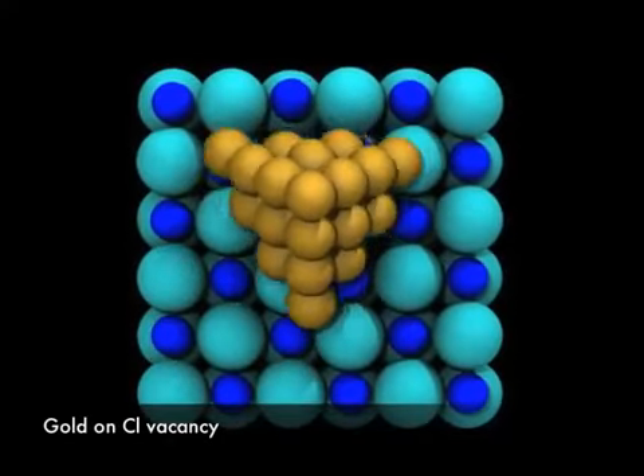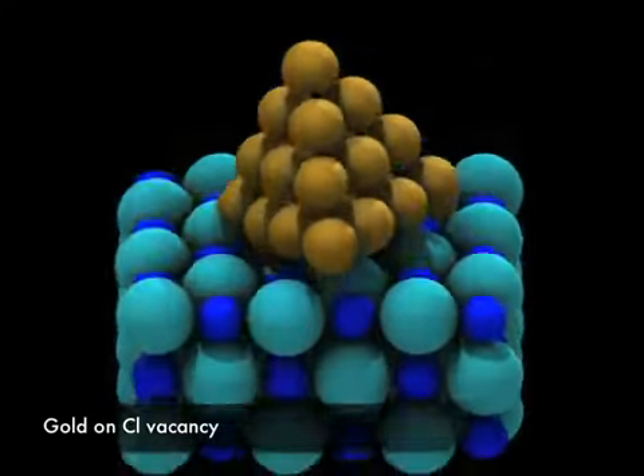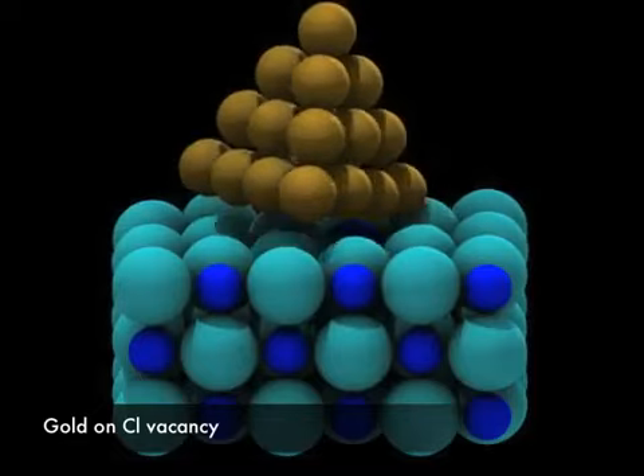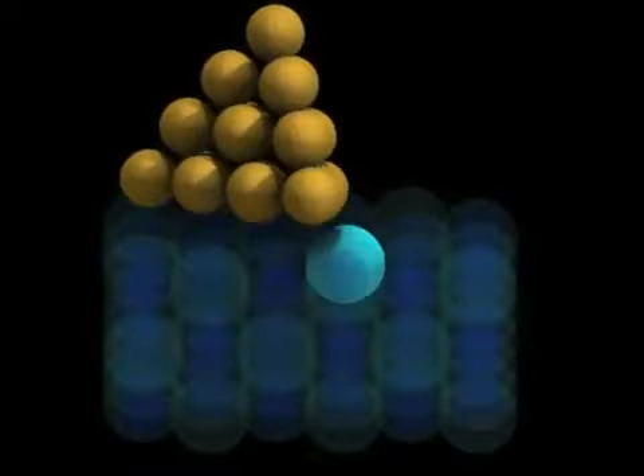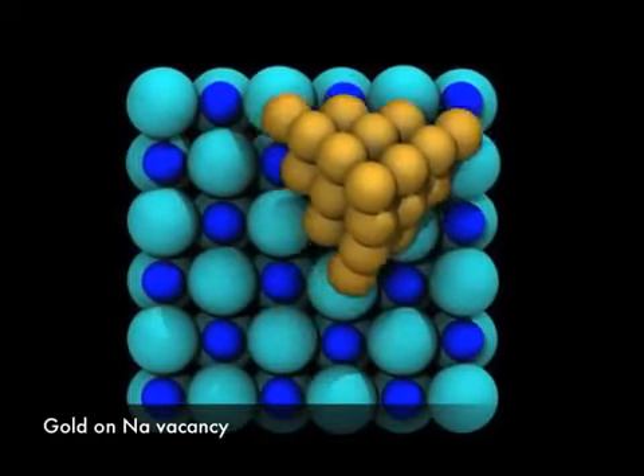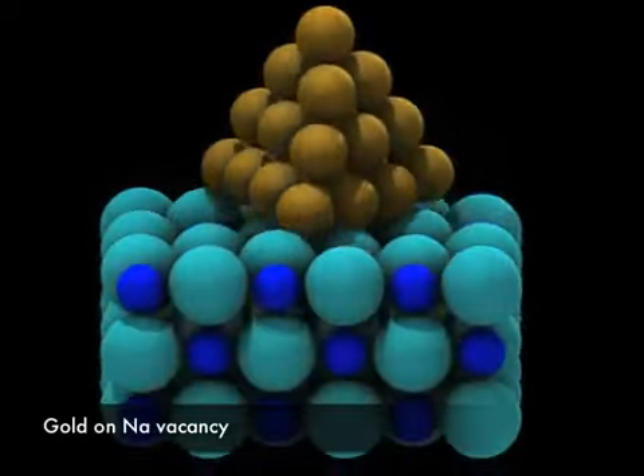Once anchored, the way the clusters prefer to move depends on how they bond with the surface, and this is determined by the type of vacancy they have paired with. Here we see the preferred pathways for a cluster at chlorine and sodium vacancies.